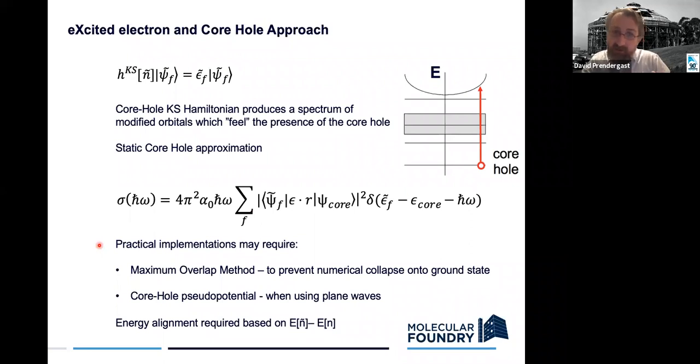Now, if you want to do this practically, as Dayu mentioned, you should try to model this excitation not in your typical unit cell, if you're doing a crystal, because that would mean that every such atom in that unit cell and all the others was excited, which is not the physical case, right? Physically, X-ray scattering or X-ray absorption has a very low cross section. So you're typically only exciting one atom at a time in what could be approximated as an infinite crystal.